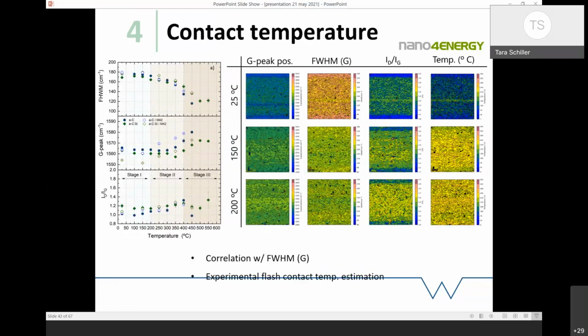tetrahedral amorphous carbon. So you use Raman spectroscopy to measure this, and again, we're measuring over a range of temperatures, as you can see here. We're looking at the change in the material and how it's affected by the amorphous carbon and the silicon-doped films. But you can see at room temperature, we don't have a heck of a lot going on. It's not until we move into the higher temperatures that we start to see the changeover with it. And you can see here, we've got some films that fail at lower temperatures than others. So you can see some are missing through here. So it's not unexpected, but a heck of a lot of work by Bruno actually running this stuff through, which is quite cool.